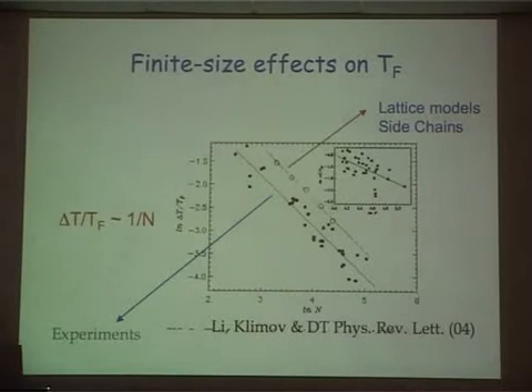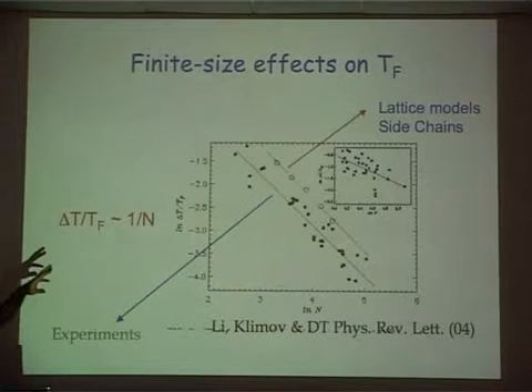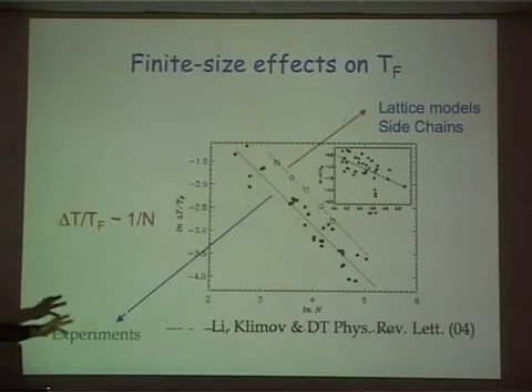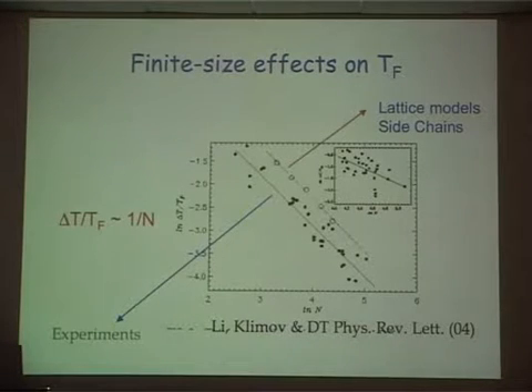Is this correct? If this is not correct, we should go home. This is a logarithm of this quantity as a function of log n, and these are for lattice models of side chains. Who cares about that? So these are temperatures, and roughly speaking, this is 1 over n. A little bit of a caution here. These data points obtained from literature experiments were conducted in laboratories all over the world using all different protocols and different kinds of error bars, and these are not the most carefully done experiments in the critical phenomena sense. If you did that, there is no question this will fall on this line, but nevertheless this correlation coefficient is quite large in fact.